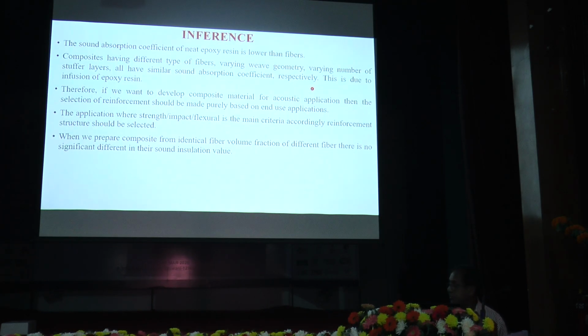So here we have the inference: the sound absorption coefficient of epoxy resin is less than that of the fiber, and composites with different stuffer layers and so on are having similar sound absorption coefficient. This is due to the infusion of epoxy resin.